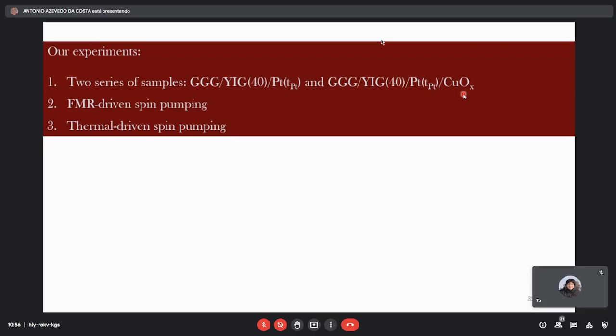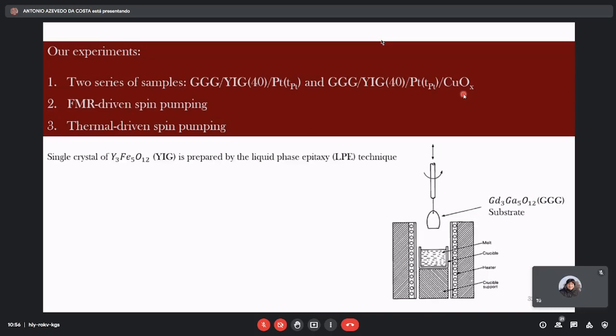And we investigated this system just by using FMR-driven spin pumping and thermal-driven spin pumping. So the YIG films are grown by liquid phase epitaxy, which is a very convenient technique to fabricate very nice films of yttrium iron garnet, and the platinum and copper were deposited by this system. And there is an important piece of information here: copper is left 2 days in contact with the air for natural oxidation.